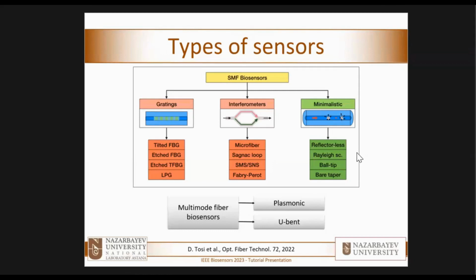You would like the sensor to work in reflection because at the end of the day, you want to build a probe. So something that, for example, you can introduce in situ rather than having to fold the fiber to run forth and back. You might place a mirror after the sensor, but first of all, that's an additional element that you're using. And depending on the distance between the mirror and the sensor, some of these techniques don't work. So that's a quite tight optimization game. A similar principle is used by the U-bend fiber. So that means you need to bend the fiber very tightly in and out.